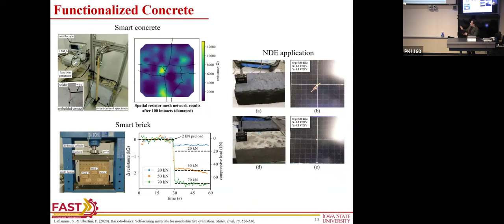These were done with, the top one carbon nanotubes, the bottom one with titanium dioxide. We use carbon black in our lab to be able to explore a large scale. Carbon black is very cheap. It's a cheap conductive powder, found in printers and car tires. And we just wanted to see if, for non-destructive application, it could give us a better signal for faster investigation of concrete, especially for roads.